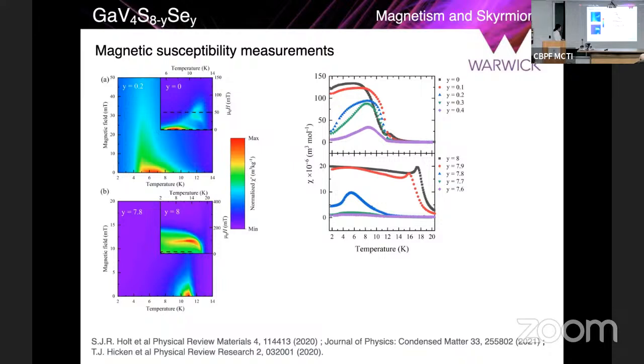One way of looking at these skyrmion pockets is to look at the dynamics of the susceptibility. So we do AC susceptibility measurements as a function of both field and temperature. So this is a very laborious measurement where you've got to stabilize at one particular temperature and scan the magnetic field, and then move slightly to another temperature and scan the magnetic field again, or the reverse. So you can build up an H-T phase diagram.